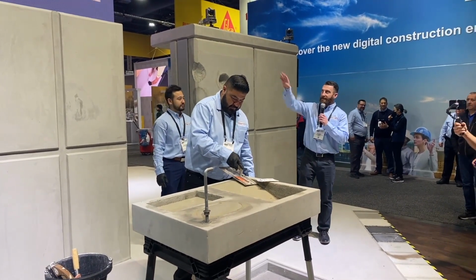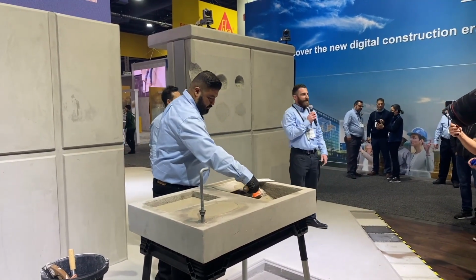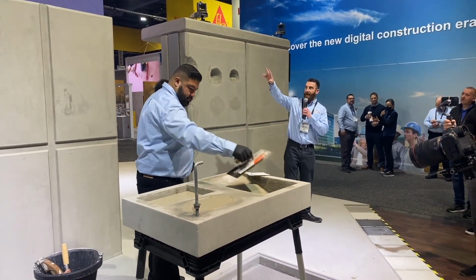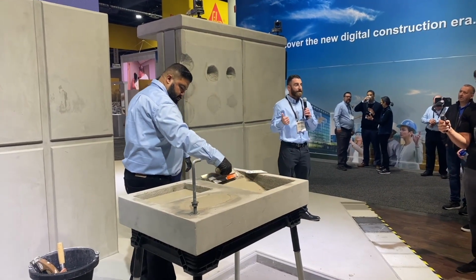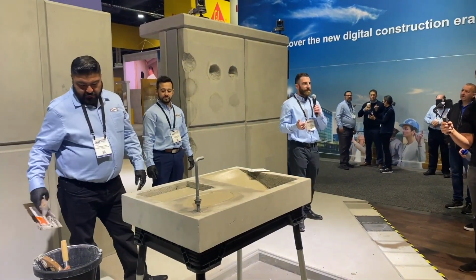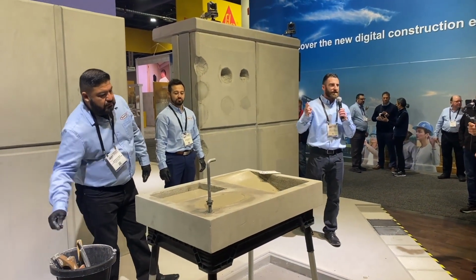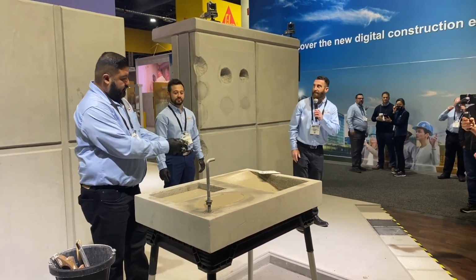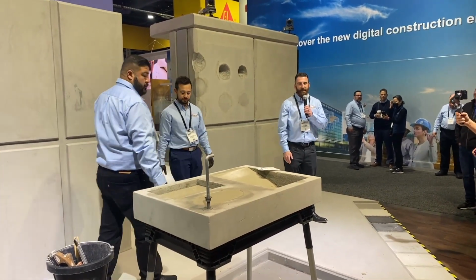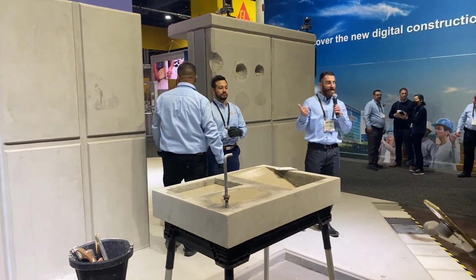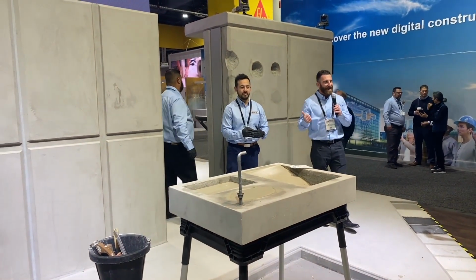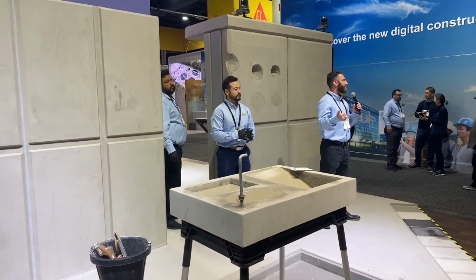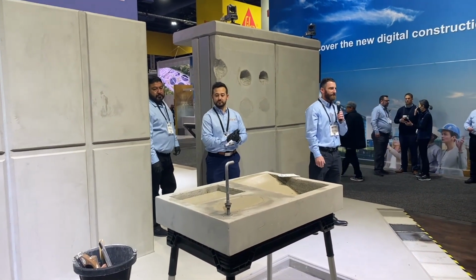So if you look up on the screen, the Highway J Bridge in Missouri, they use the Cementol to grout these keyways. And this project actually got top marks by the National Bridge Inventory for deck, substructure, and superstructure because they used the Cementol. The requirement was 3,000 psi in 24 hours, and Cementol was actually able to achieve 7,000 psi in that same time frame.